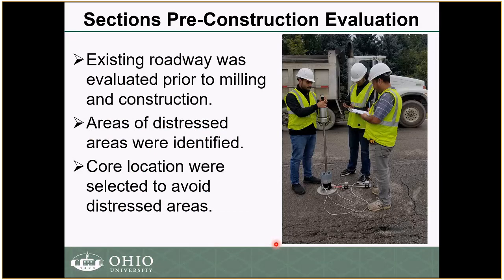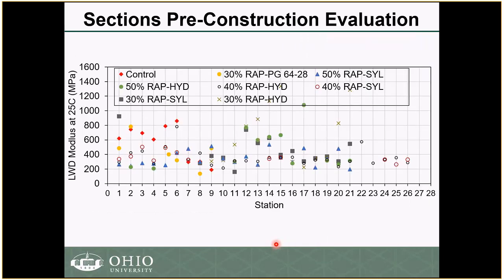So first of all, we did some preliminary testing, mainly the light falling weight deflectometer. This was done to determine where the cores should be taken so that we can avoid areas that show significant deterioration and are distressed. So we will not take cores from there. This is just the result of the LWD. We did not really see any variation between the test sections in terms of the LWD. Again, there were high and low points, but in general, there were no differences between the test sections that will affect the results in the future.